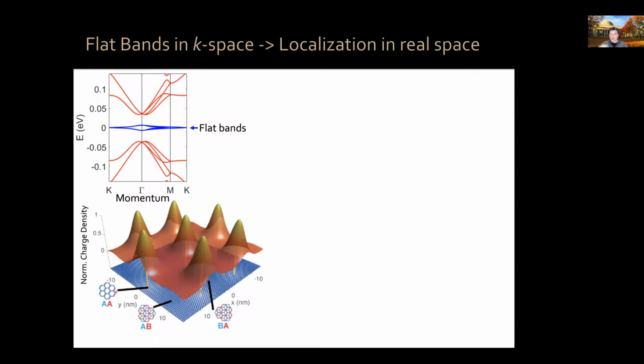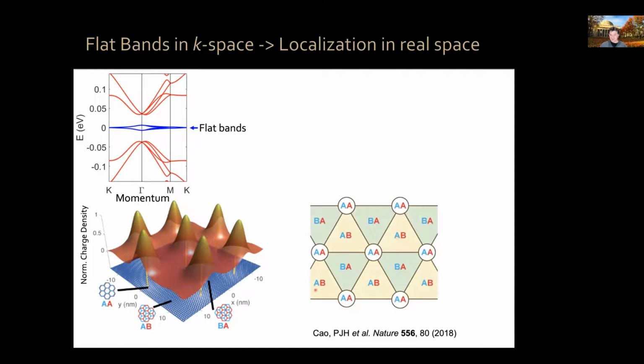Where locally all of the carbon atoms in layer 1 are on top of all of the carbon atoms in layer 2, and this is separated by regions, due to the small twist angle, of AB and BA stacking, where the electrons do not like to be. So from a schematic point of view, magic angle twisted bilayer graphene is a system where you have these AA regions where electrons like to be, and they are separated by AB and BA regions where the electrons do not like to be.